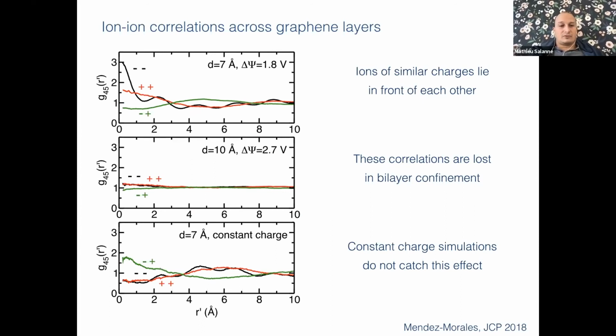And if you don't polarize your surface, so that's at the bottom, if you don't have a constant potential algorithm to simulate your system, you completely lose this. And in fact, what happens is that when you adsorb a charge, the carbon will have an opposite charge, and so it will attract again an opposite charge. So in the end, you have this kind of charge alternation. And so this is a kind of transparency of graphene, but linked only to the Coulombic interactions.